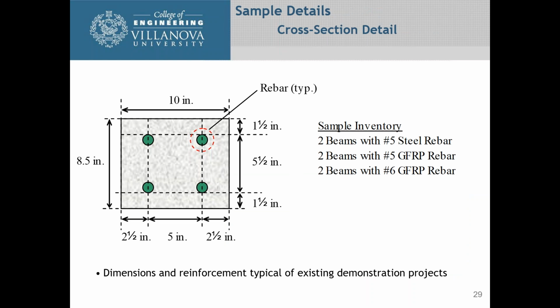So let's go through some of our sample details that we came up with. There were 6 samples that we tested. 2 beams with number 5 steel reinforcing to simulate what is actually designed now. 2 beams with number 5 GFRP bars and 2 beams with number 6 GFRP bars. We made the deck 8.5 inches deep, and we made it 10 inches wide, and the 10 inches was to simulate the 10-inch width of the truck tire.